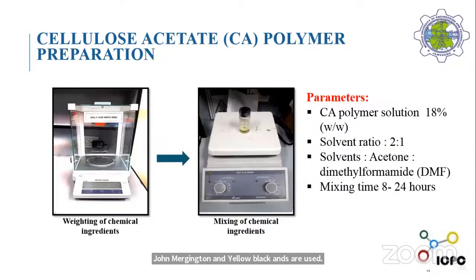Cellulose acetate, CA polymer preparation. First of all, I prepare a cellulose acetate polymer solution by using 18% weight by weight, and the solvent ratio was 2:1 to dissolve. First, I put the 18% weight by weight polymer into the solvent, acetone and dimethylformamide (DMF), to mix the solution. The mixing time was set around 8 to 24 hours to get a homogeneous mixture.